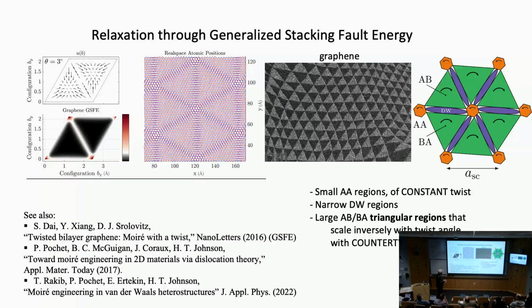The green regions untwist, twist slightly in the opposite direction from the global twist, and that allows them to be very close to the optimal stacking. And of course, there's the domain walls in between.